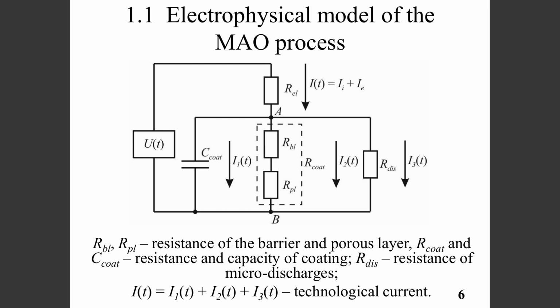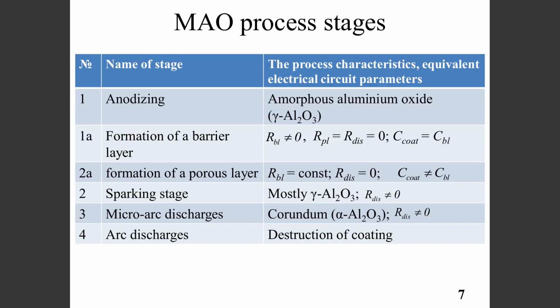The formation of micro-arc oxidation coatings occurs in a two-electrode galvanic cell, which can be represented in the form of equivalent electrical circuit shown on a slide. The initial stage of micro-arc oxidation process, called anodizing stage, can be divided into two stages. At the first, a dense aluminum oxide barrier layer, characterized by the resistance Rbl and the capacitance C coat, is formed on the anode. At the second stage, a porous layer with resistance RPL is formed and the coating capacity is the capacity of the series connections of the capacitances of the barrier and porous layer. At the sparking stage, an anodic oxide film is broken and microdischarges, which are characterized by the resistance RDs, appear on the surface of the part.